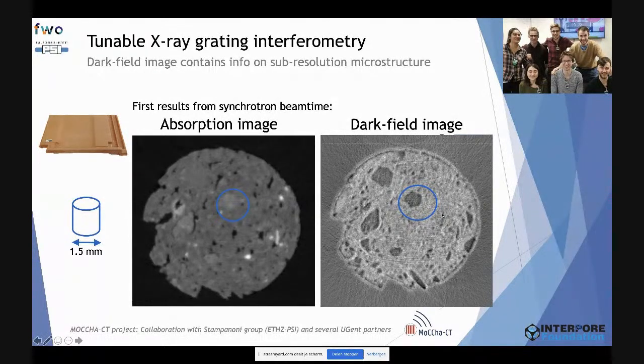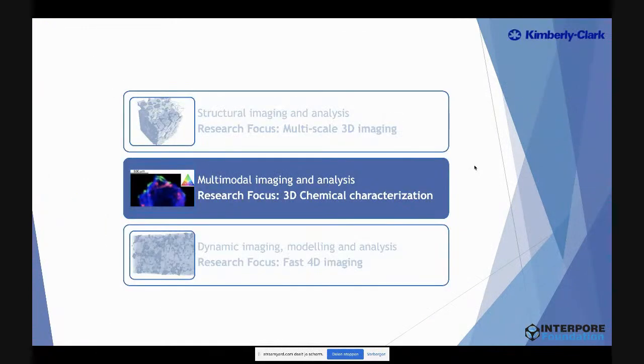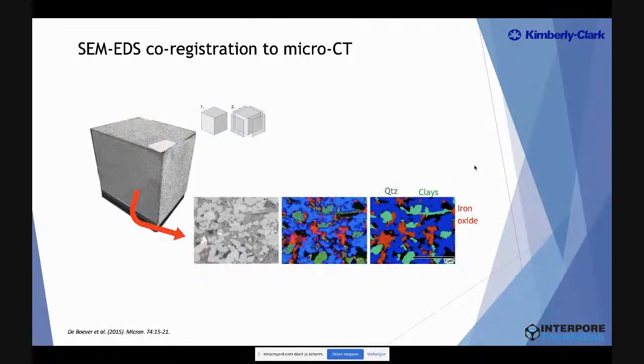And now we are working on interpreting the data in order to get a kind of automatic analysis tool for pore size distribution. Besides structure, you also need chemical information. You need 3D chemical characterization. So you can combine, for instance, CT with information of a scanning electron microscope. You can polish the surfaces of your rock, you scan it, and then you put it in a scanning electron microscope.